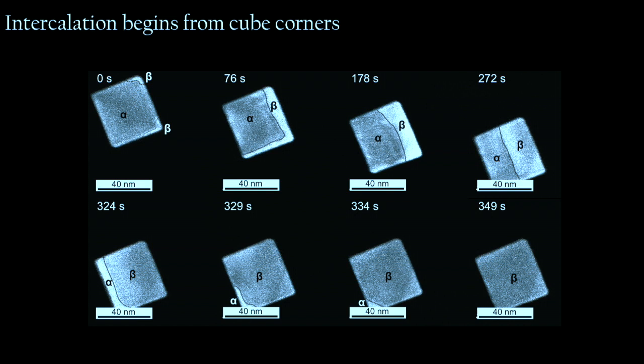I'll show you some snapshots of that video so you can see the hydrogen coming in from the corner, wetting the surface, eventually stabilizing in one particular direction, the 1-0-0 direction, and then ultimately pushes the unhydrogenated phase out of the nanoparticle. And I mentioned that there's a lattice constant mismatch between both of the phases. So you can see that as the alpha phase is being pushed out of the nanoparticle, when you look at the diffraction pattern, we wind up having two peaks, namely the alpha peak and the beta peak, that form.